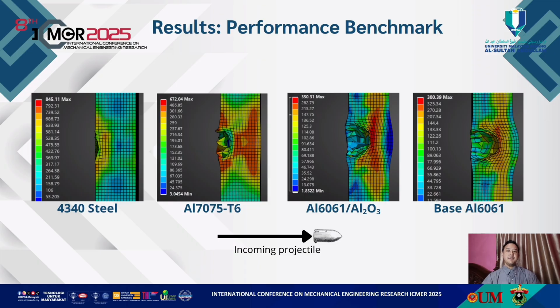In the aluminum 7075 T6 alloy plate, the high stress zone is noticeably larger and more spread out, with a more conical shape through the plate's thickness. This behavior is characteristic of a high strength yet more ductile material. This widespread distribution of stress and energy allows it to perform well, but it also results in a slightly deeper crater and larger back face signature than the steel.